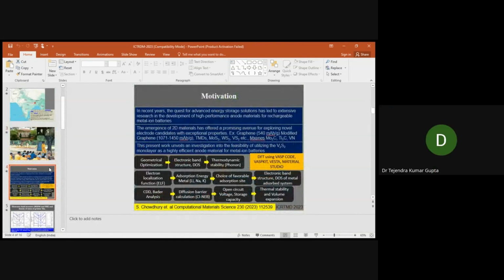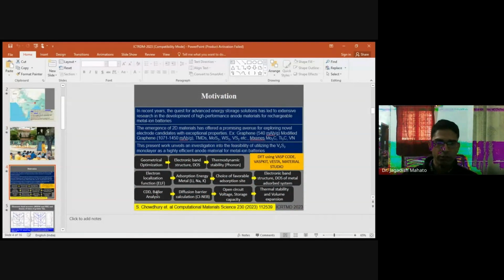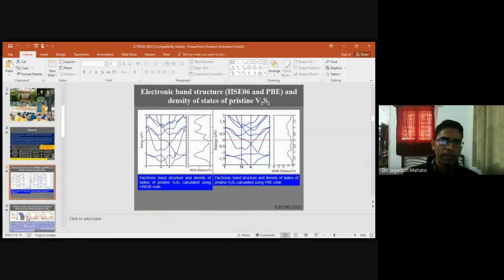So these are the steps which we generally follow, which I was just talking about. This work on the prediction or checking the feasibility of V2S2 monolayer as an anode material is motivated from the work published in Computational Material Science, which is done on the NB2S2 system, published recently. At the beginning, we do the electronic band structure calculation of the pristine V2S2 monolayer, and we see that it shows a metallic behavior from the electronic band structure and density of state calculation using the DFT VASP code.